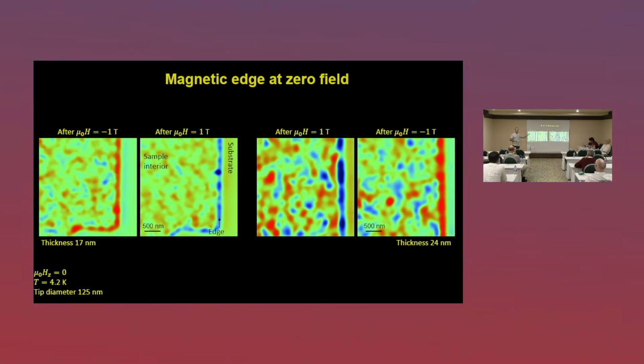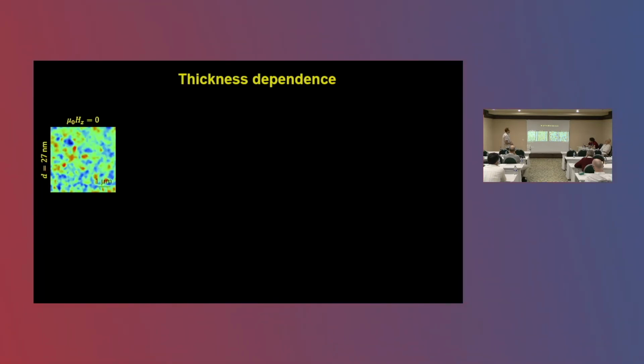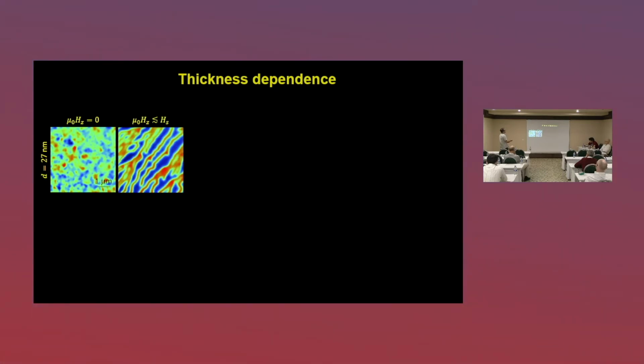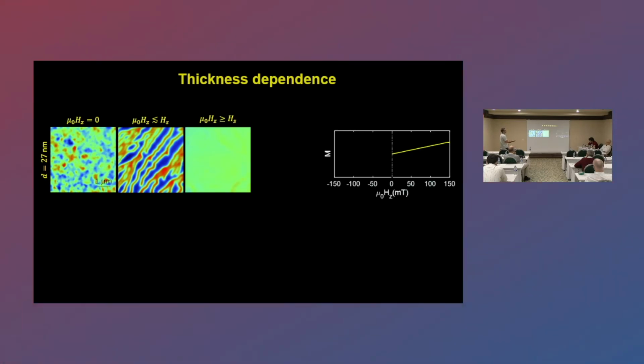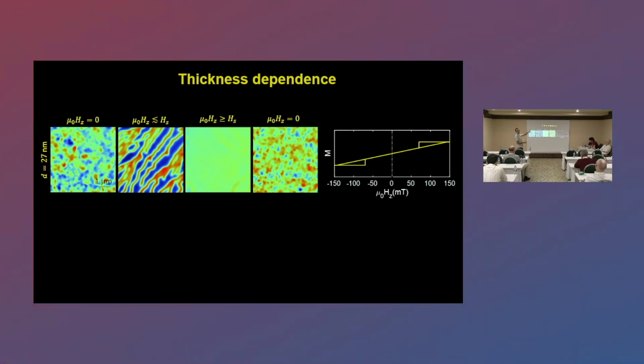So now, why would the edge be magnetized? The truth is, we don't really know, but we have a hint maybe. We also looked at the behavior of the interior as a function of thickness. So this is for very thick. We said there is no magnetization here. When you increase the field, at some point it magnetizes, and I can draw this with my hand, a magnetization that goes up until it saturates. If I go back to 0, it stays magnetized, and at some point it demagnetizes and stays here. So I can just anti-symmetrize this picture. We call this the bow tie magnetization curve.